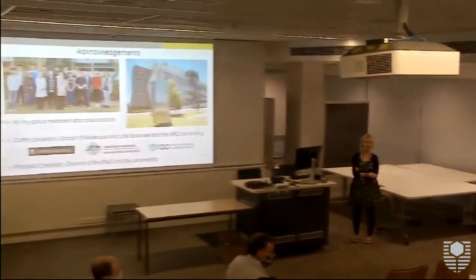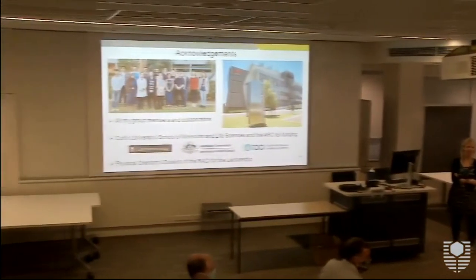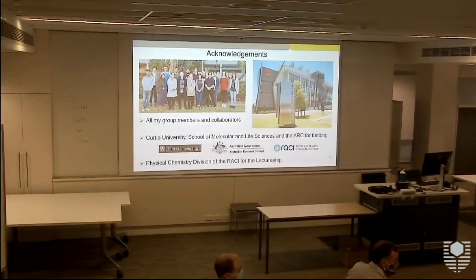A couple of things. In a previous life, I worked for Rio for about 30 odd years, and there's two things. You're right about your lightning element. Also, if we had a truck go under an overhead power line, what you immediately do is put a 100 metre radius around the truck, and no one goes near it for 48 hours, because that reaction does take a long time. So an oxygen sensor in that may be of a lot of value.